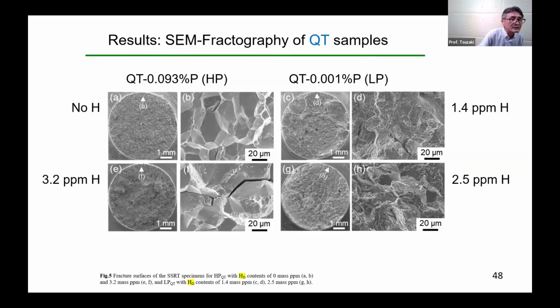This is the result of SEM fractography of the QT sample. In QT 0.093% P steel, grain boundary fracture was observed at the crack initiation site, even without hydrogen charge. On the other hand, in QT 0.001% P steel without hydrogen charging, although it isn't shown here, dimple fracture was observed in all regions of the specimen. As hydrogen content increased, 1.4 and 2.5, the ratio of quasi-cleavage fracture and intergranular fracture at the crack initiation site increased, as shown in D and H.